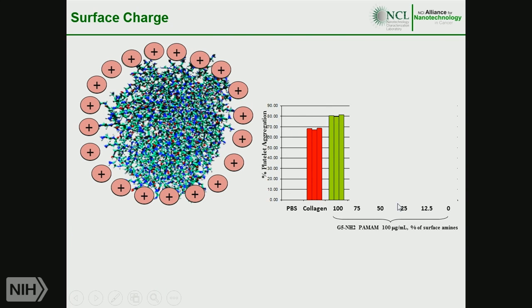Particle surface charge, as I mentioned, is also an important determinant of particle biocompatibility. Again, I will use the platelet aggregation assay as an example, and my model particle in this case is PAMAM dendrimer. This study was done in collaboration with Dr. Anil Patri. What Anil did, he used the generation 5 PAMAM dendrimer, which we knew activates platelets and induces platelet aggregation. It's a very potent activator.